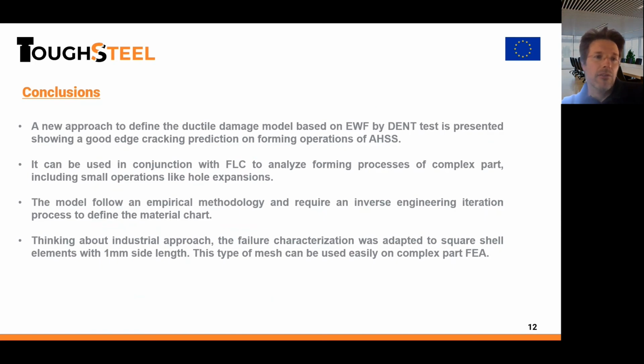Okay, finally, in conclusion, a new approach to define the ductile damage model based on the essential work of fracture by dent test is presented, showing a good edge cracking prediction in the forming operation of the new advanced high strength steel. It can be used in conjunction with the FLC to analyze the forming processes, and we can also use it, for example, for hole expansion with the limitation of diameters. The model follows an empirical methodology and requires an inverse engineering iteration process to define the material card.